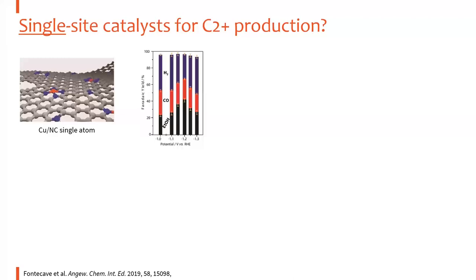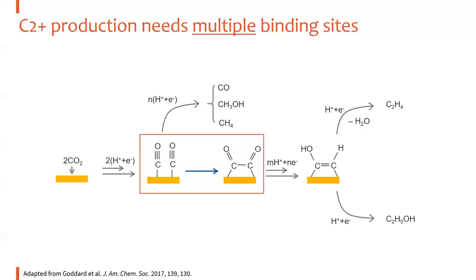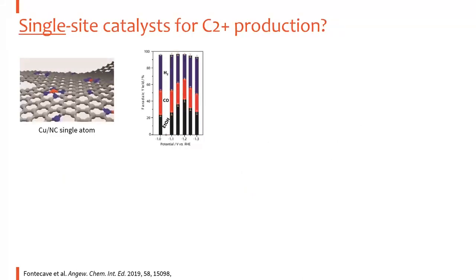So whether a single site catalyst can catalyze C2 product production is actually a mystery, because we cannot understand how this happens. Here is the widely accepted mechanism for C2 product generation. Starting from CO2 accepting protons and electrons, it needs to go to an intermediate called CO. Only by coupling two CO, or COH sometimes, can we generate the C2 intermediate. And the C2 intermediate is the starting point for us to generate the C2 products. Otherwise, we can only generate the C1 products. So we need to have at least two active sites to bind such CO intermediates so that they have chances to couple. But for the single site catalyst, theoretically we only have one active site, which means it's almost impossible to generate a C2 product.